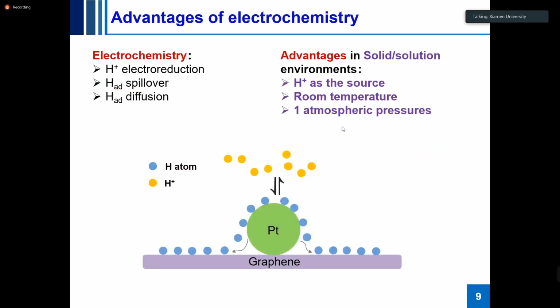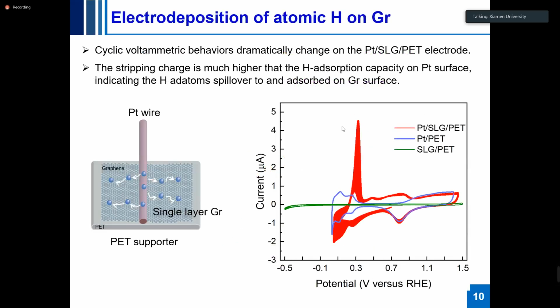So we are electrochemists, so we use electrochemistry. When we use electrochemistry, we can use protons as the precursor. The protons are reduced electrochemically by the platinum catalyst to form hydrogen atoms. The atoms spill over from platinum to the graphene and then reside there. So this experiment can be totally performed at room temperature with 1 atm pressure. So this is the experiment.